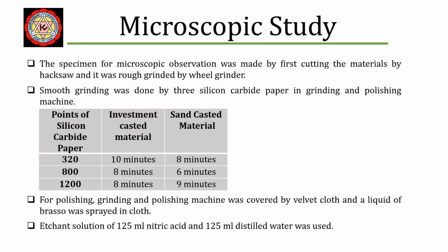At last, a microscopic study of both sand casted and investment casted specimens was done. The specimens for microscopic observation were made by cutting the materials, and smoothing and grinding was done by three silicon carbide papers in the grinding and polishing machine. This table shows the time for which smoothing was done on the different grades of silicon carbide paper. For polishing, the grinding and polishing machine was covered by velvet cloth and a liquid of brasso was spread on the cloth. An etchant solution of 125 ml nitric acid and 125 ml distilled water was used.